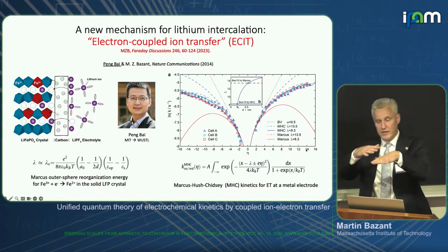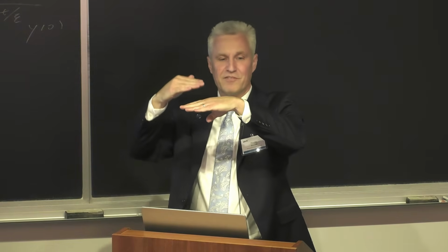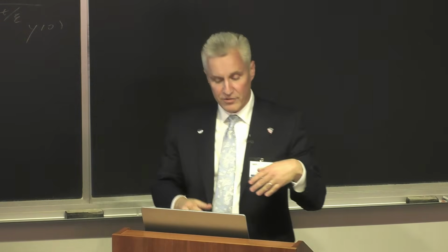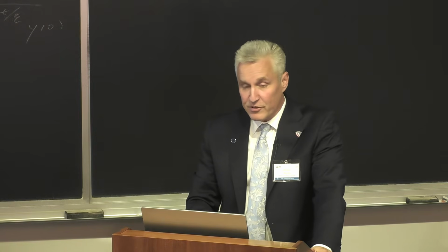Nice thing about LFP also, it has a very flat voltage plateau, so you know exactly where equilibrium is, and so you can more easily measure what the overpotential actually is. Anyway, we plotted all this data, and amazingly, it was a perfect fit to Marcus theory, actually. So we were kind of blown away by this.